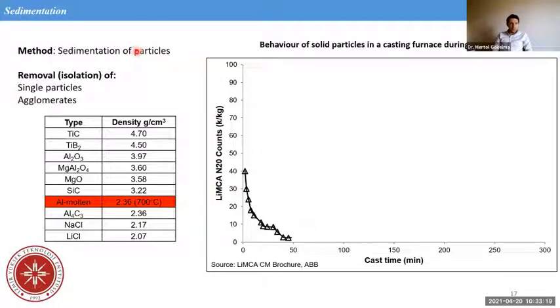So the sedimentation of particles does removal or isolation of single particles and agglomerates. Here you can see approximately the densities. Molten aluminium has 2.3 approximately at the melting point, and a bit above this at 700 degrees, which is the typical processing temperature of aluminium, 700, 720. And in aluminium production, we avoid going over 740-50 because the oxidation behavior of aluminium changes after that temperature and is not as stable as it is at 700 degrees.